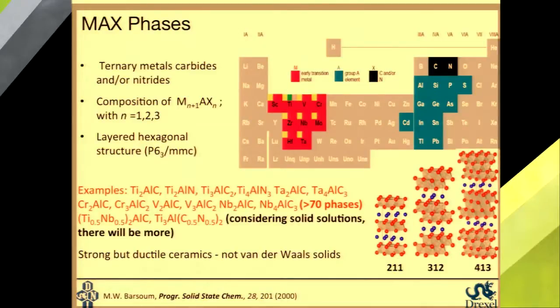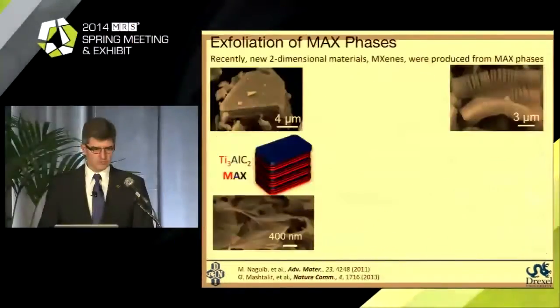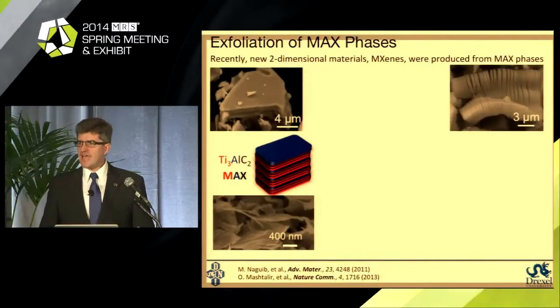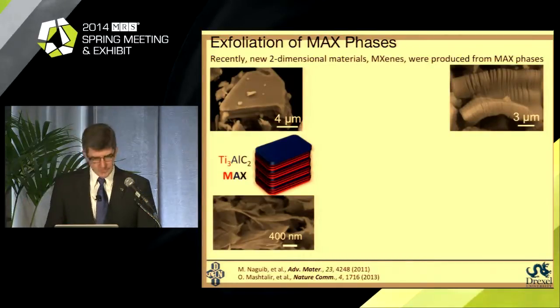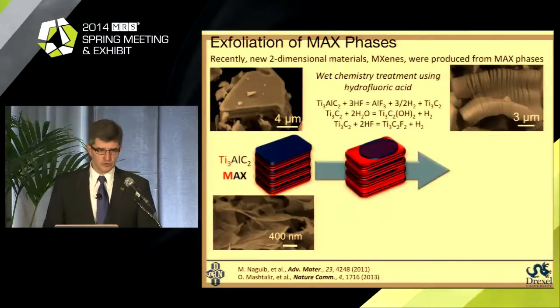And there are many of these materials, some produced commercially. More than 70 phases have been synthesized and studied. You can consider them very simply as a single, double, or triple layer of carbide separated by a monatomic layer of A element atoms. So what we did was fairly straightforward. We etched away this monoatomic layer of metal, specifically aluminum, from titanium aluminum carbide, by initially etching with hydrofluoric acid.